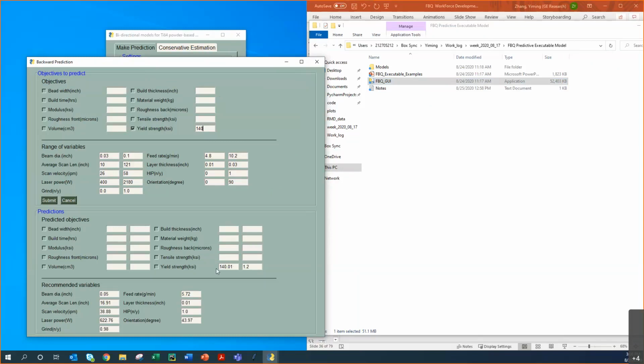Now the backward prediction is done, and the yield strength is predicted to be 140.01 KSI, with a standard deviation of 1.2. The bottom sections will show you the recommended parameters. For example, the build diameter is 0.05, and the feed rate is optimized to be 5.72. If you compare with the range of parameters, they are strictly within the identified range of variables.